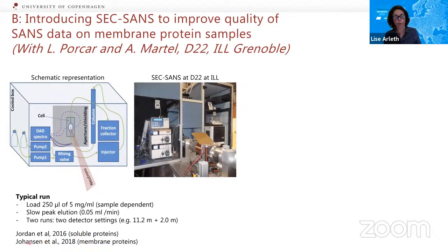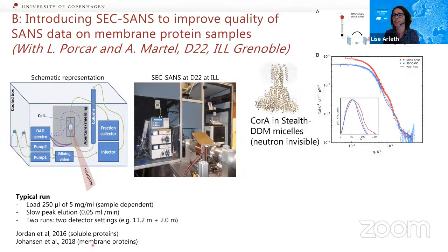And we then built on this work and used the same approach, and also showed that we could use the technique in combination with much more complicated membrane proteins. And this really becomes an advantage in combination with the stealth deuterated detergents, because then we can exchange from hydrogenated to deuterated detergents on the column. We can put the visible membrane proteins, with the visible hydrogenated carriers, into the column, but what comes out are the invisible versions, because we make this exchange of the DDM over the column here.